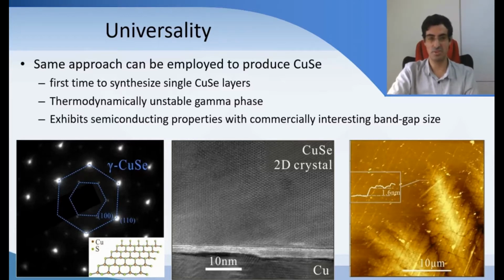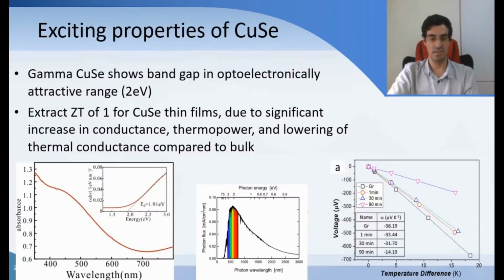This is exciting because CuSe has kind of unexpected properties. First, we're seeing it has a band gap of about 2 eV, which is interesting for optoelectronic devices like light emitters and solar cells. And it also has a fairly high Seebeck coefficient. So the thermopower and the ZT from that thermopower is about 1. So it might be interesting for energy generation or energy harvesting. So these are advantages of 2D materials and the ordering that they induce on materials that you grow on them.